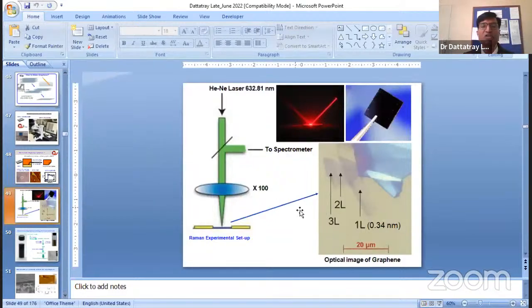And these are some of the other optical images where you can identify, just by optical contrast, whether the transferred graphene layer on SiO2 is really 1-layer, 2-layer, or 3-layer graphene. Just see by color contrast. Of course, these are multi-layer or kind of graphite, because more than 10 layers is like bulk material, right? So graphite kind of thing. This is a very interesting and very simple technique to transfer a monolayer of graphene from bulk graphite.